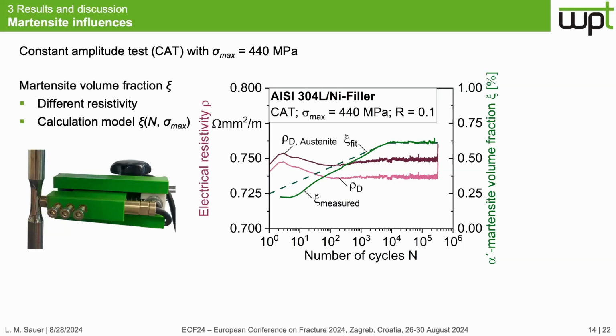And the increase at the beginning indicates a significant microstructure change at the beginning of the fatigue test. For example, an increase in the dislocation density, or a formation or deformation of voids, but as I mentioned, it's not possible to clearly say what kind of change this is. I can only say that there are significant changes, and during the fatigue test, there are only minor changes in the electrical resistivity, which indicates that there are only minor changes in the microstructure.